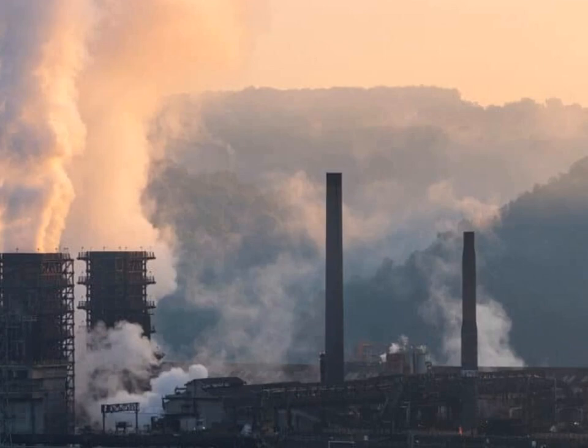First, fly ash. This is a fine powder left over from burning coal in power plants. Okay, a waste product finding a new use. Precisely. And the data showed that replacing 25% of the cement with fly ash can cut the concrete's total CO2 emissions by about 13% to 15%. Its own emission factor is quite low, around 0.027 tons of CO2 per ton, mostly from processing and transport after it's produced. 13 to 15% reduction just by swapping out a quarter of the cement. That sounds pretty good. It is, and it's widely used.